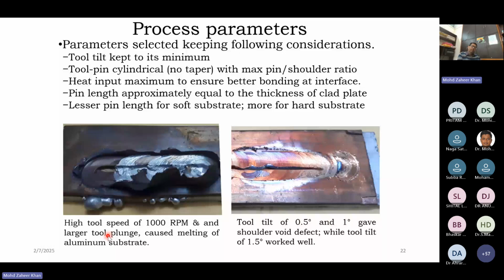We had no previous experience of this, so we tried a range of process parameters, and there were some failures that helped us in gaining insight into the material. One problem was that when the tool RPM was very high, like 1000 RPM, and a large tool plunge was there, the temperature was excessive and the substrate, which was aluminum, actually melted and started to flow out, and a complete disaster was created, as you can see in this figure. Similarly, when the tool tilt was 0.5 degrees or 1 degree, this type of tunnel defect was created, and this is also a complete failure.